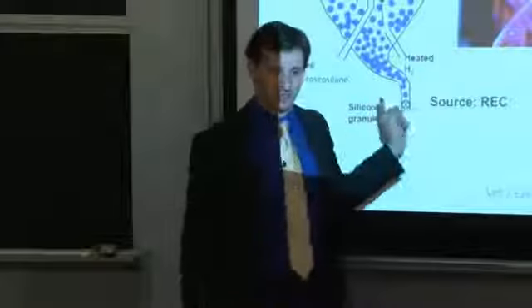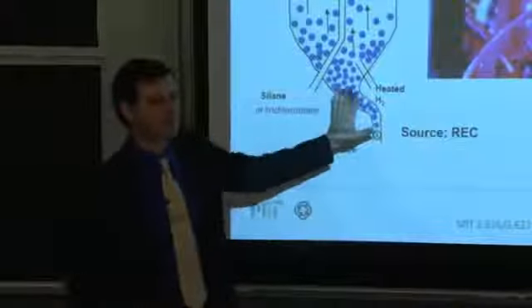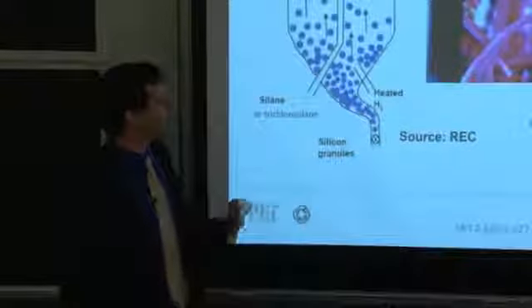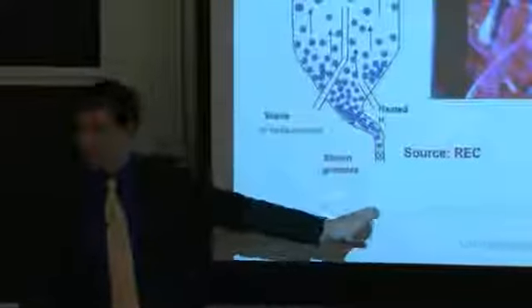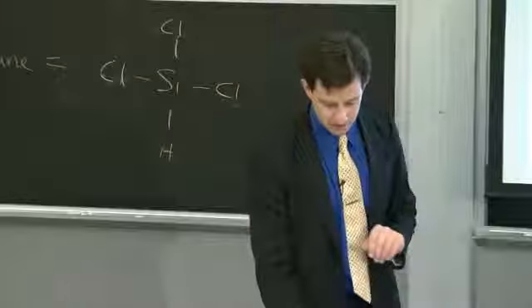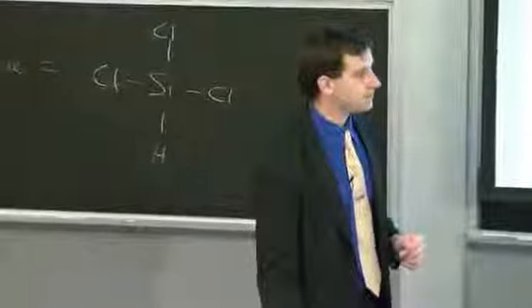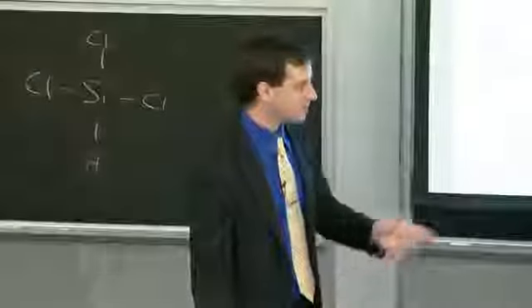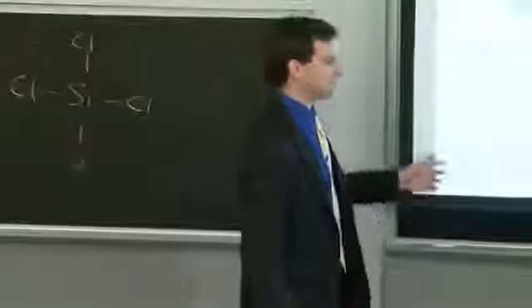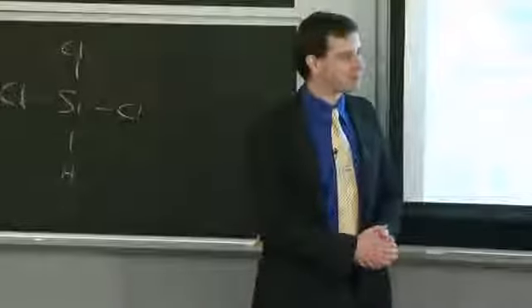As a result, the energy intensity is lower, the cost is lower, but it's a very tricky process to nail, to get just right, because you have to get the gas flows right, you have to design the chamber well, reduce impurity contents. It's a tricky process. And so this is being produced right now, I believe, by only a few companies. REC has the capability of doing it. MEMC as well has the capability of doing this process. By and large, most silicon is coming from the Siemens process. Sorry, both of those companies have the normal refining process. They have the normal refining process too. Yep, and that's why they developed this new one. They had these smaller internal projects that were able to develop them.